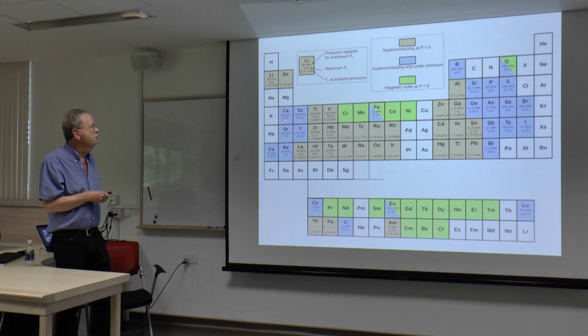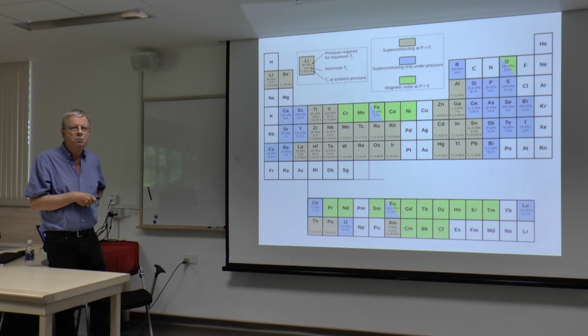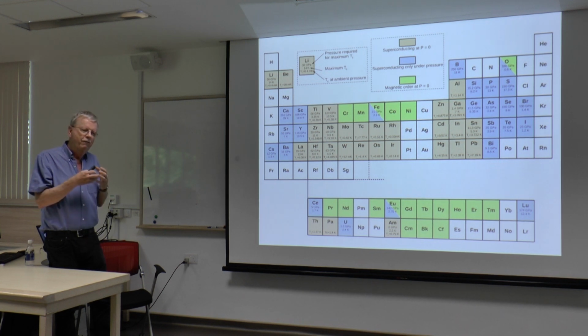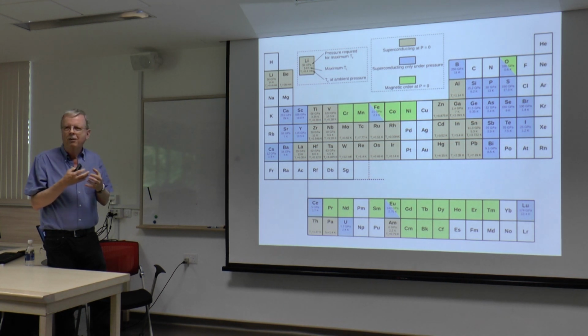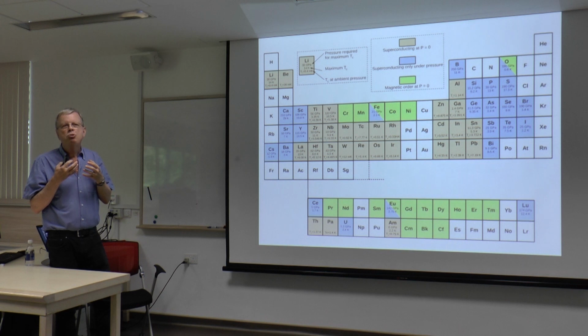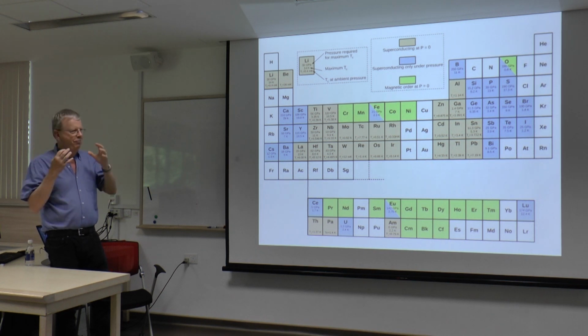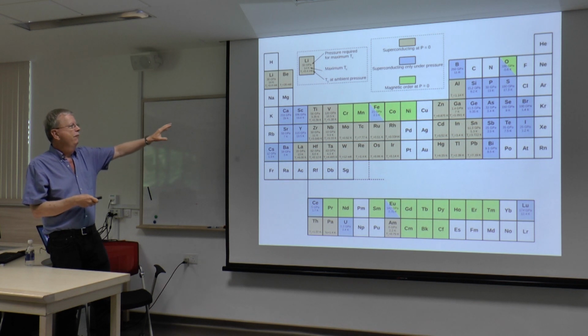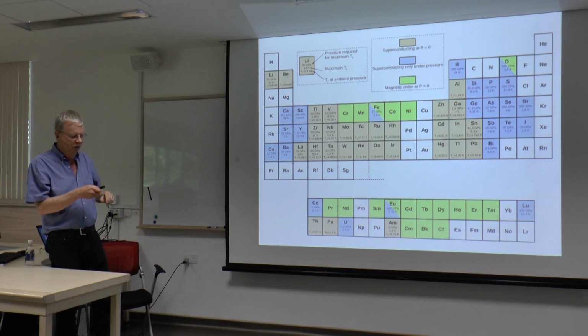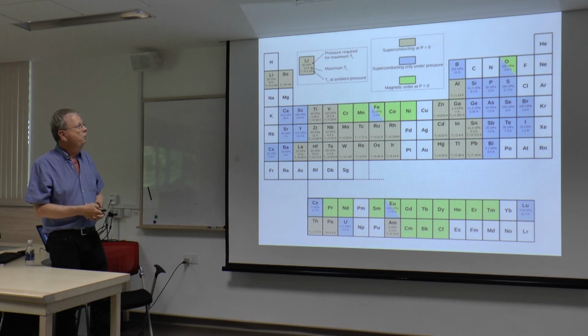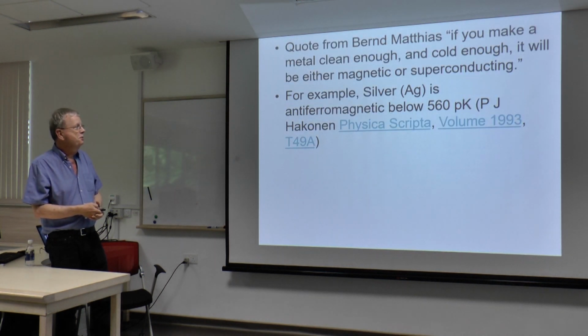I mean, the fact that calcium superconducts at 29 Kelvin at 2.15 megabar, I'm not sure we're all caring about that. Back in the 70s, I was working with someone who was doing A15s that didn't want to form in that structure except under high pressure. We were happy with a megabar, and we got that from plastic explosives down in one of the canyons. So the fact that someone can DAC put on 2 megabar is a lot of work. So this graph shows you that the frontier of where superconductivity might be, a la Matthias, is rather open. And of course, silver is a nice low temperature record.